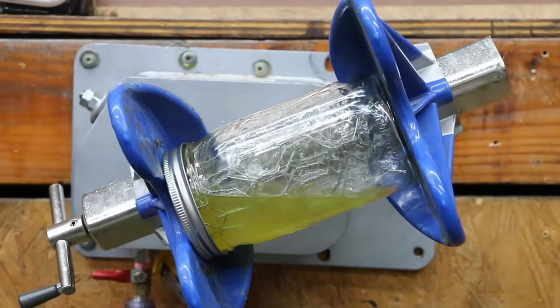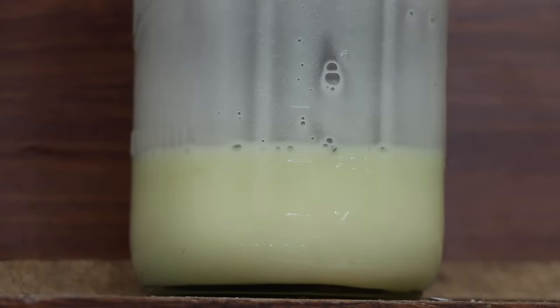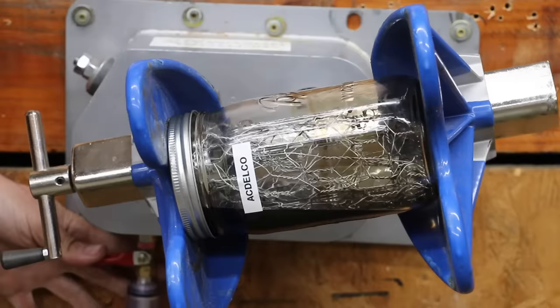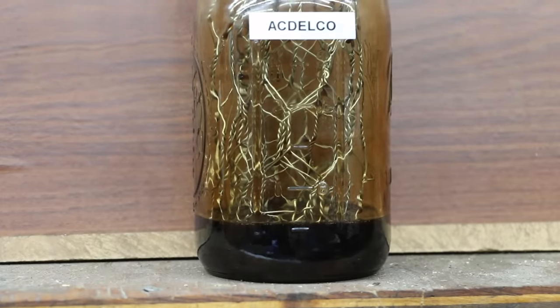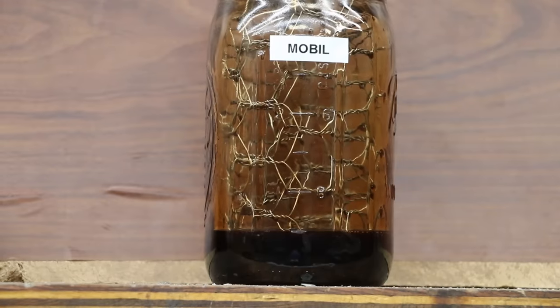While the transmission fluids prepare for the cold race, let's compare the cooked fluids for foaming. All transmission fluid should have anti-foaming ingredients that prevent bubbles from forming. Testing oil without anti-foaming ingredients first shows a lot of air mixed in after just a few seconds — inside an automatic transmission, this could cause damage from oil starvation or clutch slippage. The AC Delco refused to foam and passed the test. Supertech also performed very well, lasting the entire five minutes without air bubbles. Mobil held up just fine without foaming. And Redline also passed. All four transmission fluids offer very good protection against foaming.